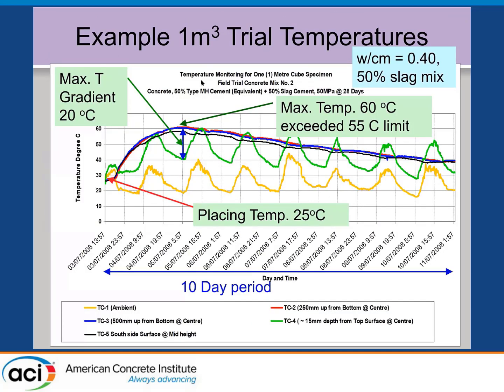So for example, here's a mix with 50% slag. They were looking for a 55-degree maximum, but it was exceeded. This one didn't quite make it. They were looking for a 20-degree C maximum gradient through the cross section between the inner and the outer part. They made that. In this case, the placing temperature was 25, or about 78 degrees Fahrenheit. And this shows over a 10-day period what's going on. Here's the ambient bouncing around. Here's the near surface bouncing around. And here's the core going up and then back down again over a 10-day period.